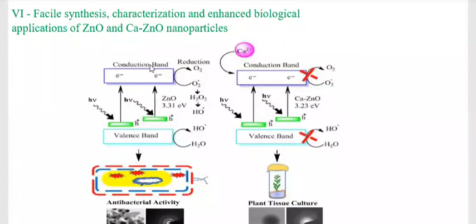This one, ma'am. The facile synthesis and characterization to enhance the biological application of zinc and calcium doped zinc oxide nanoparticles. The zinc oxide nanoparticles show a band gap of 3.31, and when you add calcium doping, 3.23 electron volt. Zinc oxide nanoparticles show very good antimicrobial activity, but calcium doped zinc oxide reduces the antimicrobial activity and enhances plant tissue culture. This is the theme of this slide. Next slide, ma'am.